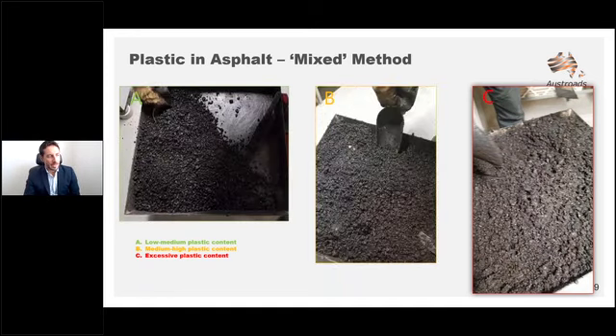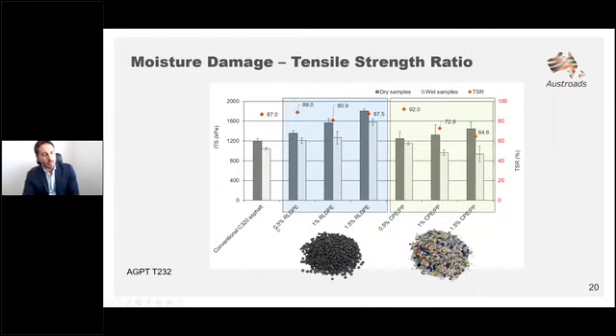behavior. Now, in terms of moisture damage, we looked at the tensile strength ratio of the different mixes. In the blue zone here, you have the post-industrial plastics. In the green zone, you have the post-consumer type of plastics. Well, the first thing to notice is that within the post-industrial plastics, the results were quite consistent and I would say high, above 80%. Usually in Australia, 80% is kind of the threshold value for assessing the tensile strength ratio. Obviously, there is an increase in the dry tensile strength of the mix.